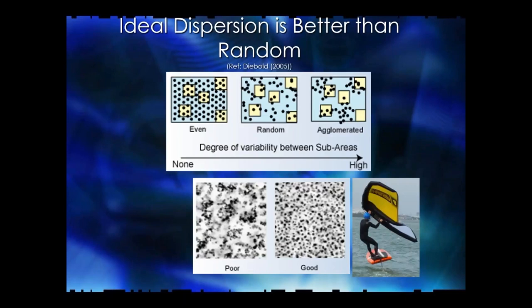What we want to have for the ideal hiding power is a product where the titanium dioxide is uniformly dispersed. If we have these high refractive index light-bending particles uniformly distributed, on the right we have something that we call good dispersion. Most people, as they converted to 100% water-based systems, have this in their paint coating. So the titanium dioxide manufacturers go to great pains to make a quarter micron particle size. Why a quarter micron size? Because that's half the wavelength of blue light, and that gives you the best scattering of the light.